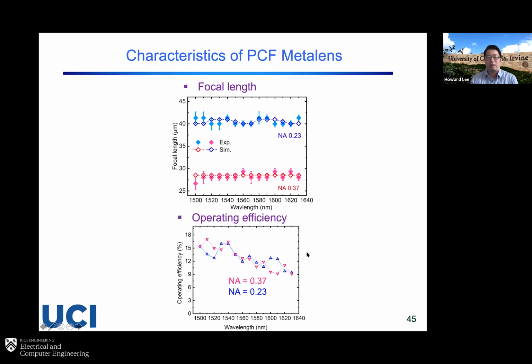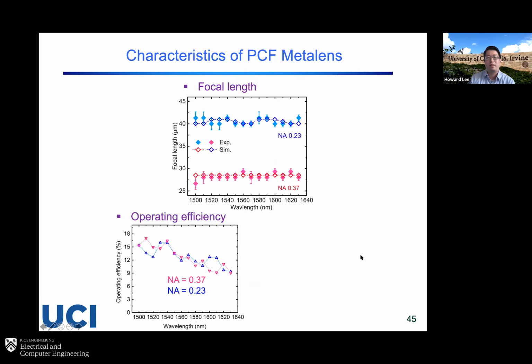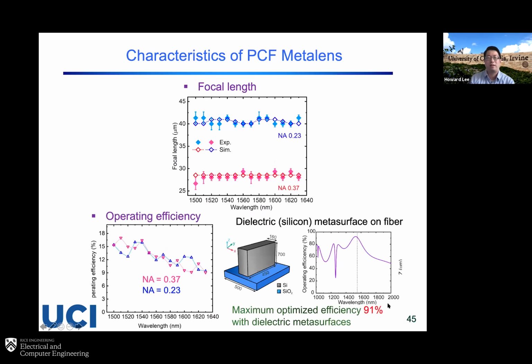So this is already quite good for a metallic structure because you have some losses induced in the metallic structure. But what we find is, if we make a dielectric metasurface, actually we can make the efficiency much higher, around 90%. So, which is something we have been currently working on, making a dielectric metasurface to enhance efficiency, which is somehow a little bit more tricky because we need to use E-beam lithography to pattern this dielectric metasurface, which is something we have been working on.